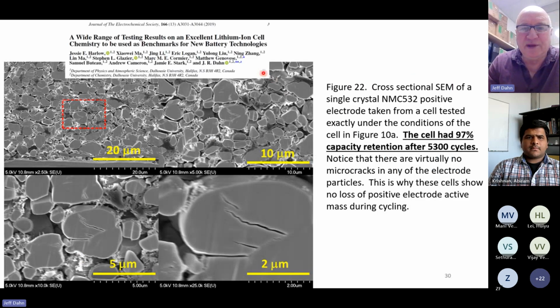This is a figure from a paper that we wrote doing cross-sectional SEM of the positive electrode of single crystal positive electrode material after 5,300 cycles. When you look at the majority of these particles, there's no cracks at all. This one big one that we follow along has this one massive crack, but the rest of it isn't cracked at all. So these single crystal materials are amazing.